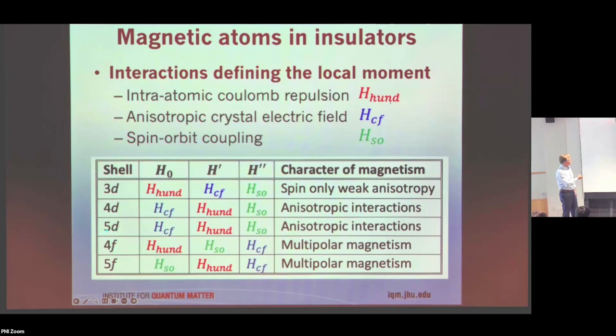When you come to 4f electrons, the intra-electronic repulsion and spin-orbit interaction is very strong, generating a spin-orbital degree of freedom, and then crystal field excitations will eventually lift that degeneracy. In some cases, specifically for rare earth ions that have an odd number of electrons, you can have a ground state which is a Kramers doublet. They don't have to, but they can behave pretty much as a spin-half degree of freedom. And that's the kind of spin degree of freedom that turns out to be possible to realize on a triangular lattice with next-neighbor interactions in a set of compounds called delafossites.